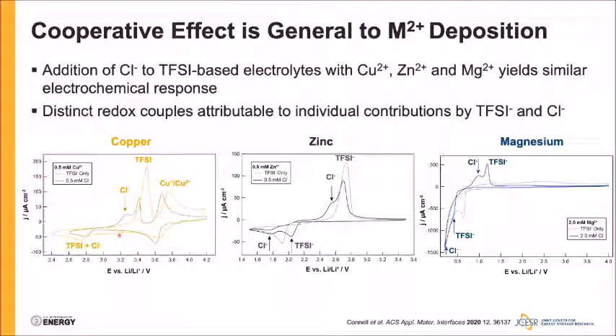And what we see is that indeed, if we add chloride to a TFSI-based electrolyte, we see more or less identical behavior for copper, zinc, and magnesium. We see the appearance of additional redox features upon the addition of chloride, both for copper and magnesium, that look very similar to what we see in the zinc systems.